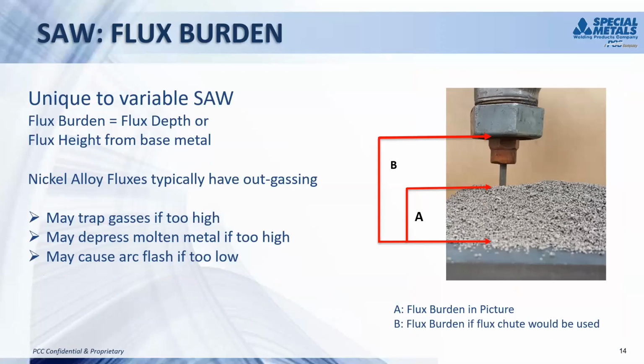But with nickel fluxes, you typically have some outgassing, so you have to balance that height. If the burden is too high, you can trap some gases. There's some weight of that flux that can actually depress the nickel metal, and you get some very interesting phenomena where the metal will actually be oozing out the sides of the weld, and you've got flux coming out the side, and it just makes a very big mess where you don't typically see that with a steel submerged arc flux.